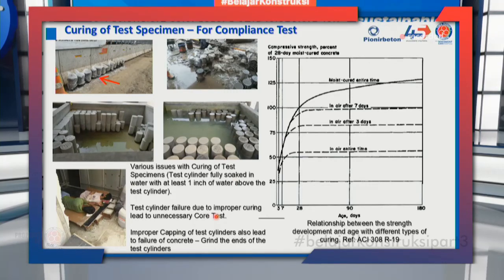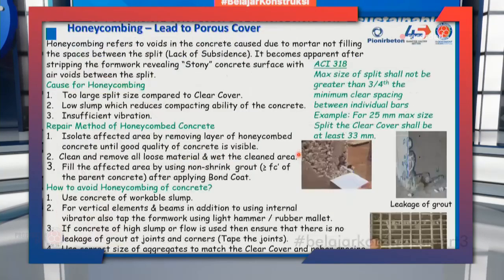When you core it, you are basically destroying the original quality of the concrete. And this you have to remember here: what happens if I don't cure for 28 days? If I cure all the 28 days, this is my strength. For 7 days, it's only 90%. If it's 3 days in water, then afterwards in air, it is only 75%. If it is entirely air, it is only 55% of the target. That should not happen.